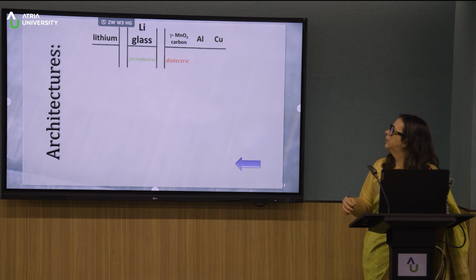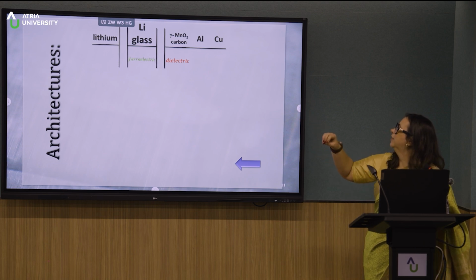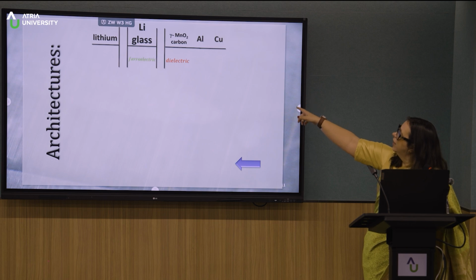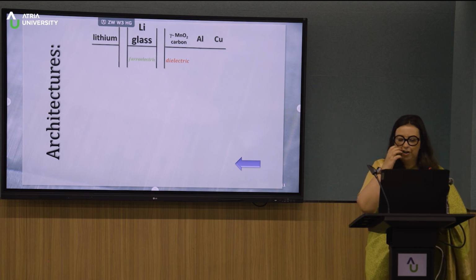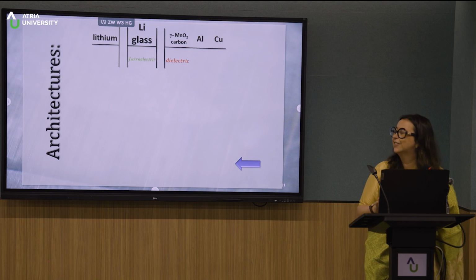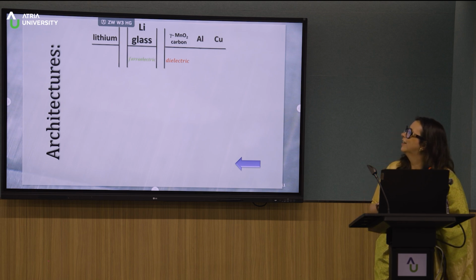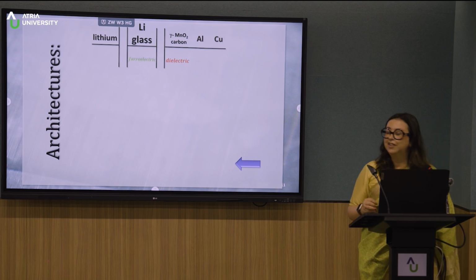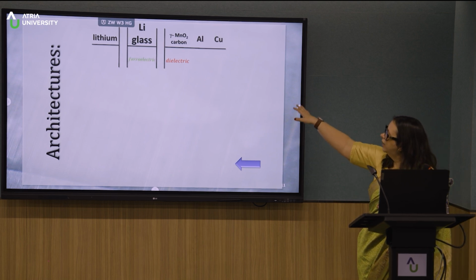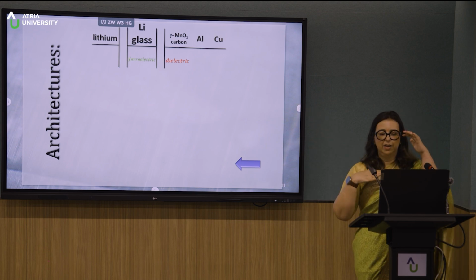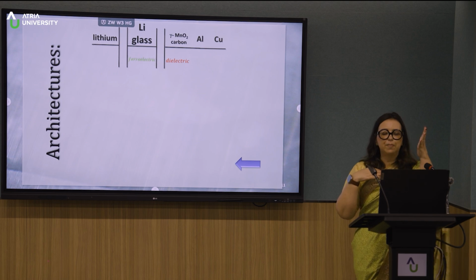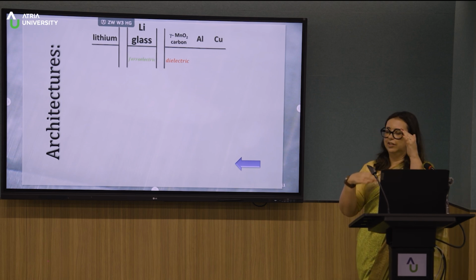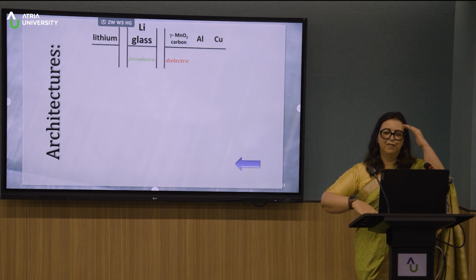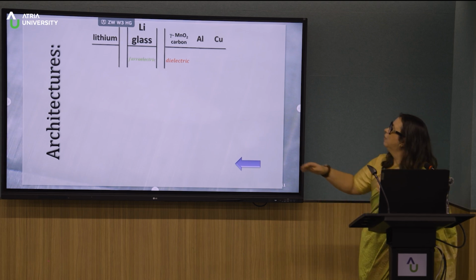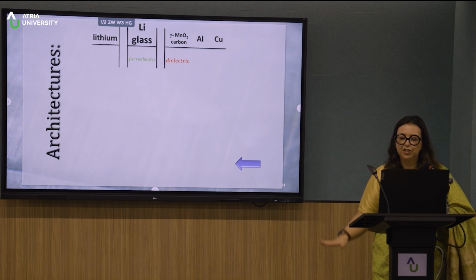We've made a lot of architectures. This is more of the traditional architecture. But on this side, instead of putting just the aluminum, we put in the copper. Why did we put copper on that side? This was just to study. We were not yet trying to be sustainable, in that this will make the battery more expensive, but what we wanted to do is to bring the chemical potential down so that we had a bigger imbalance between the positive electrode and the negative electrode, because this is what the voltage of your cell is all about.